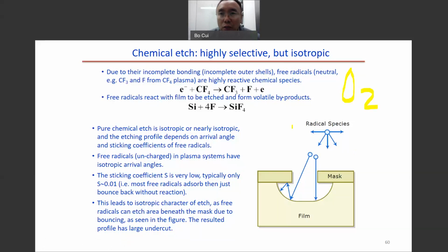The etching rate is also fast, but the etching is isotropic. That means etching something like this. So you may wonder how you can etch the material below the mask. If the free radicals come like this, it still can etch below the mask. This is because the free radicals have a very low sticking coefficient. It's called sticking coefficient. That means, for example, 0.01, that is 1%.